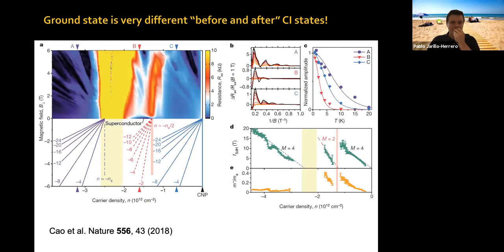So this was already present in our original 2018 papers. For example, we had seen that in the Landau fan diagrams, if you look at the resistivity versus magnetic field and carrier density, and you look at your Shubnikov-de Haas oscillations, here is the correlated insulator state. This is charge neutrality. This is the band insulator.